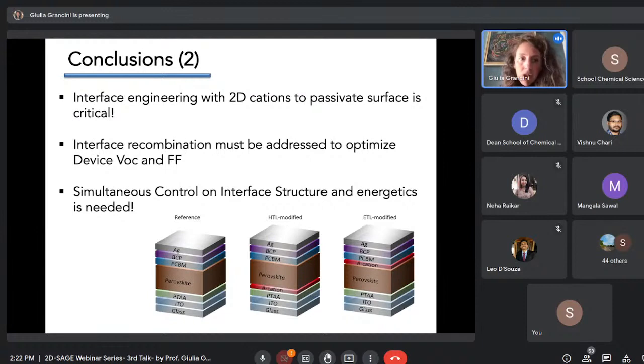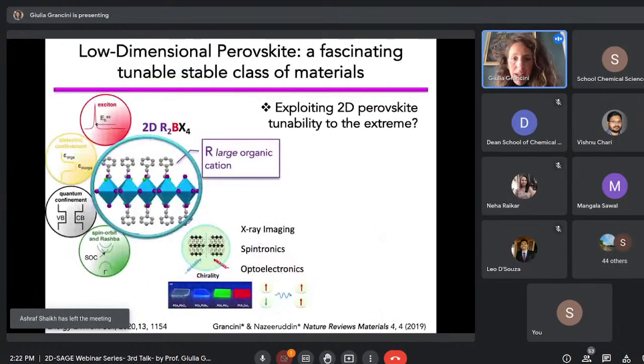It needs a lot of attention and simultaneous control of the interface structure, but with this method, you can reduce the interface recombination and improve device VOC, fill factor, along with the device stability, which is very crucial. And now I would like to move a little bit out of solar cells, and show you in my last few minutes an example of exploiting this class of 2D perovskites, which are an extremely fascinating class of materials because they are extremely tunable, not only for solar cells, but also for other applications like light-emitting devices.